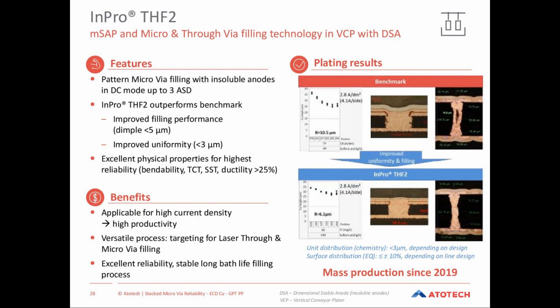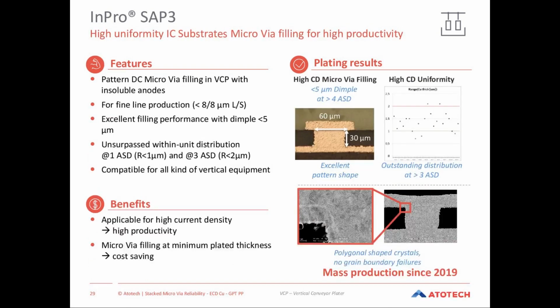For vertical through-hole filling and in combination with micro via filling, you see here the latest process InPro THF2. Only to show you the improvement itself from the standard process to this new generation of through-hole filling, you can see here at really practical current densities of 2.8 ASD, we get with the new process, THF2, a very good micro via copper filling, and we can mostly prevent inclusions in micro vias or in through holes. Even in through holes which are very narrow and not perfectly drilled, we get much better inclusion-free results. This is a nice combination.